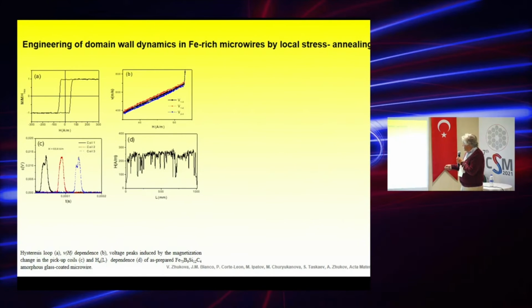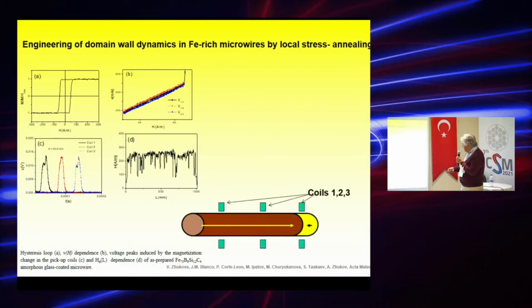One of the examples which we published recently in Acta Materialia is this: this is the as-prepared material. This is the dependence of domain wall velocity on magnetic field, and you can see that it's quite linear and quite high. We measured it using the Sixtus-Tonks method. Once the domain wall passed through the pickup coil, you can see these peaks in the pickup coils reflecting that the domain wall moves along the sample, like shown in this picture. So first, second, and third coil.